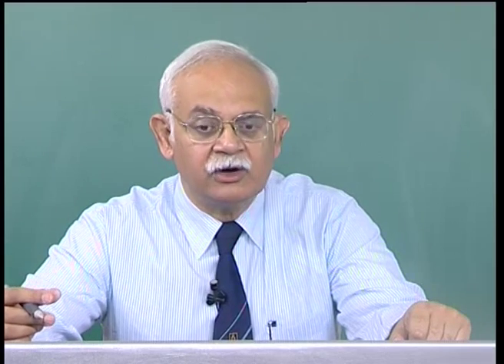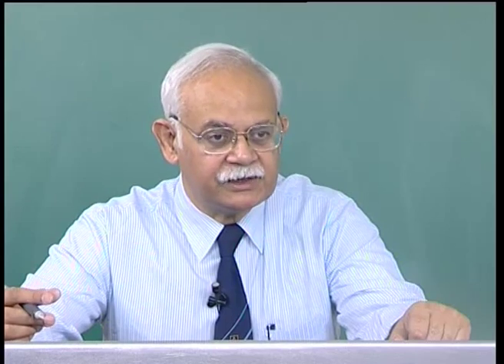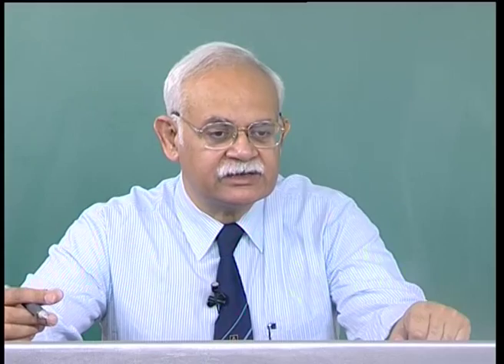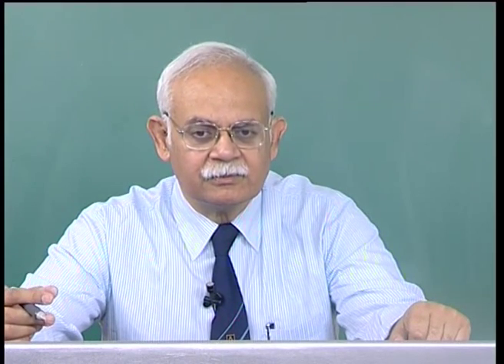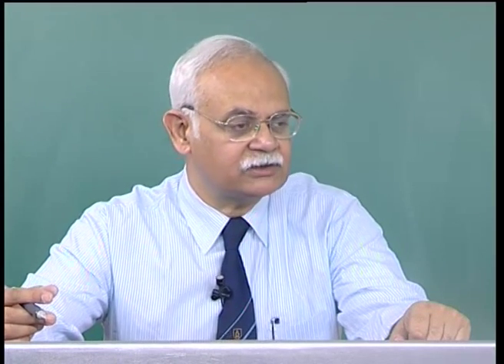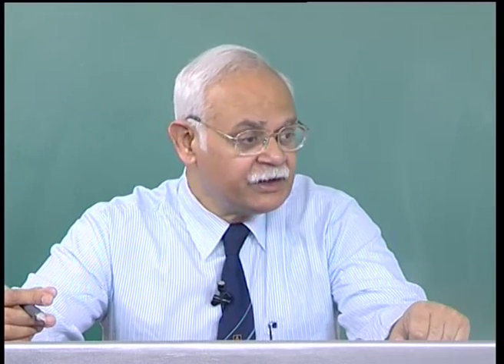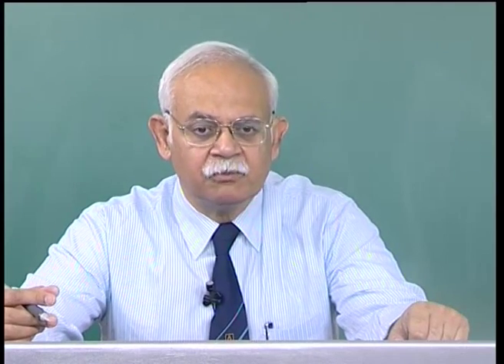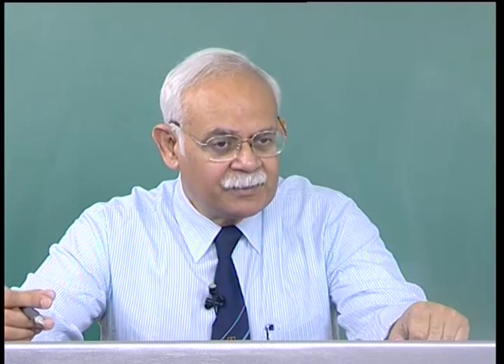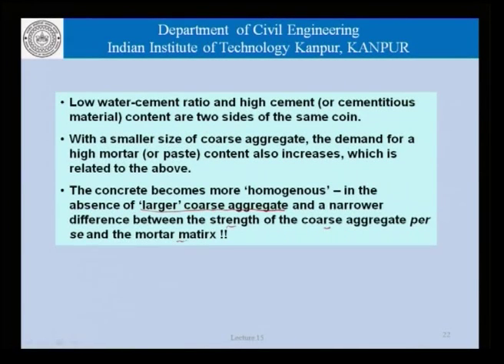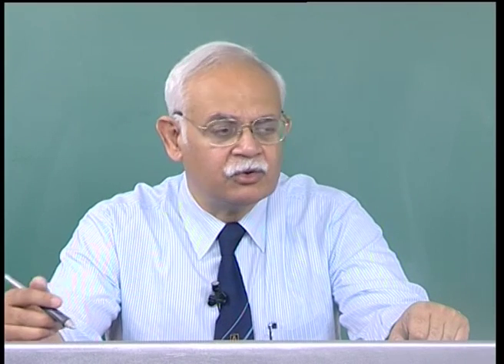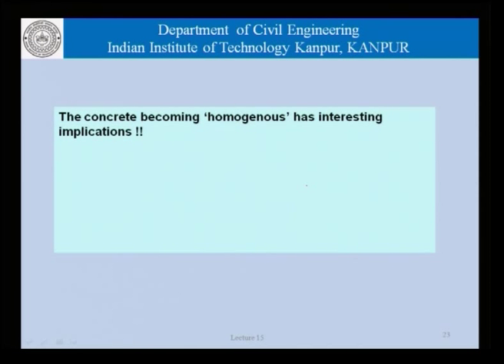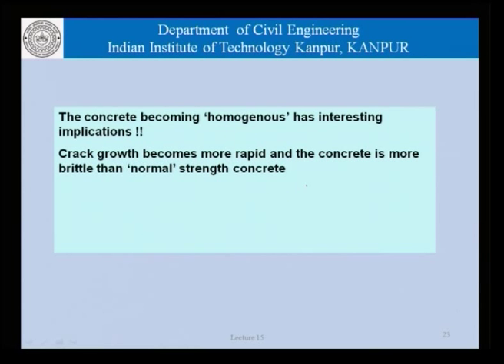Those of you who work or who have a background in finite element analysis would understand this concept very simply. In order to assume that concrete is homogeneous, you are making an assumption that the aggregates and the mortar and the ITZ have all the same strength, which is obviously not true. So, if we are able to remove the larger coarse aggregates, the concrete becomes more homogeneous, and also the gap between the strength of the coarse aggregate and the mortar matrix is narrower. So, in comparison to normal concretes, high strength concretes are more homogeneous. Now, this concrete becoming more homogeneous has very interesting implications. Crack growth becomes more rapid and the concrete is more brittle than normal strength concrete.